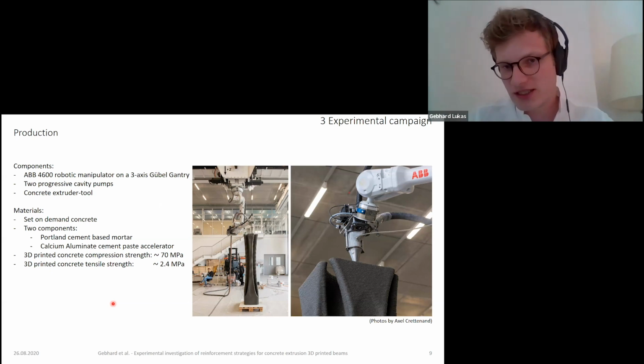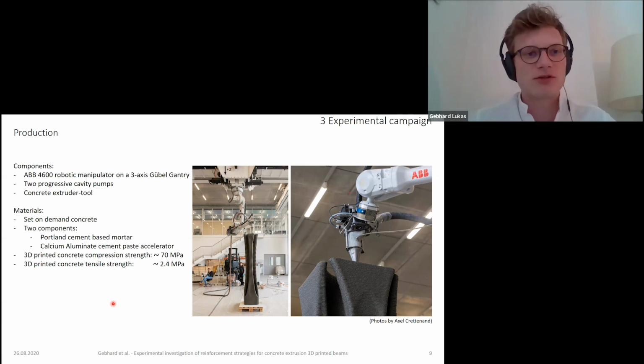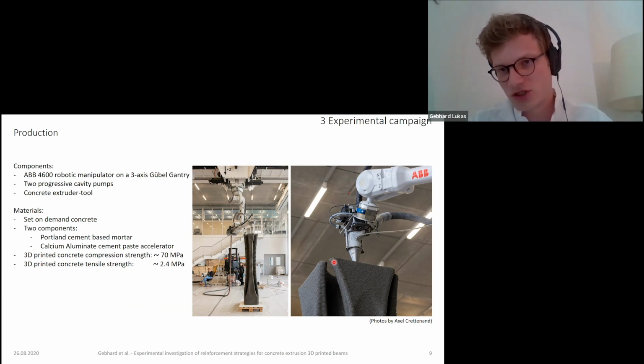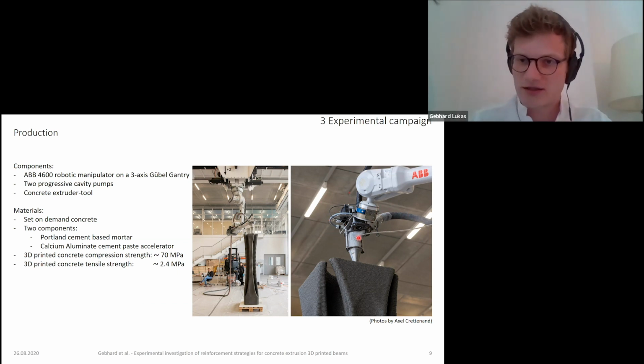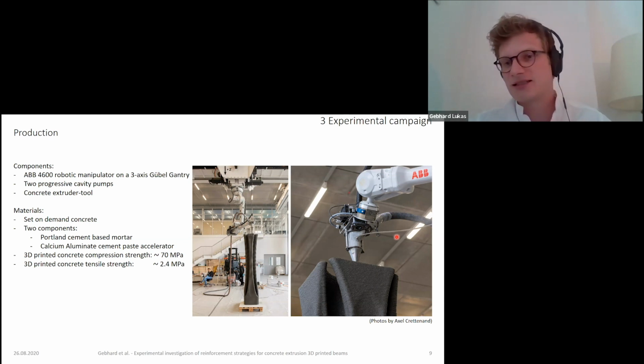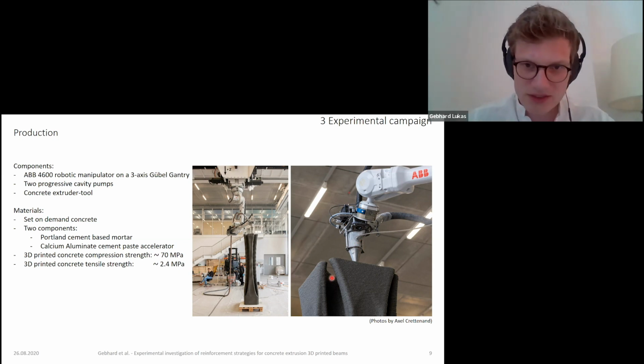Now about the production and our 3D printer. This 3D printer is an ABB robot on a 3-axis gantry and is fed 2 materials by 2 progressive cavity pumps. And then we have this extruder tool that you can see on the right on top, where we have the big hose for the mortar and the small hose for the accelerator. And this is a set-on-demand system where we have the mortar as Portland-based cement mortar and the accelerator as a calcium aluminate cement paste. And then we printed these beams.